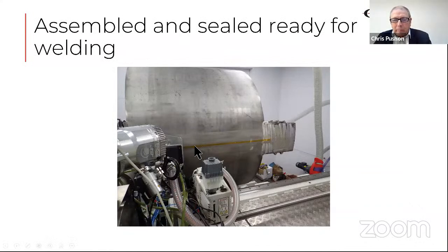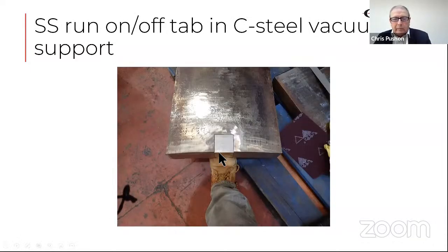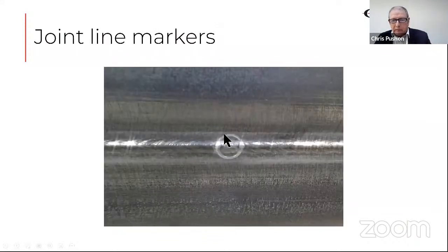So here's an example of the setup. We seal the joint with just a piece of self-adhesive tape, which normally in a high vacuum system you would never get away with. This is the stainless steel run-on, run-off tab. We use a circular beam oscillation to increase the effective diameter of the beam, but also to put a witness as to where the weld is. And that leaves a mark on the surface. So when we go to inspect the weld, we have a target to say the weld line is right in the middle of that circle.